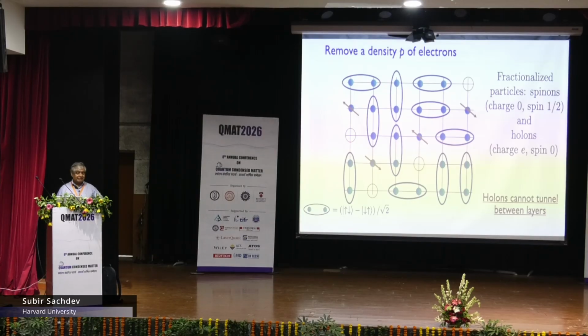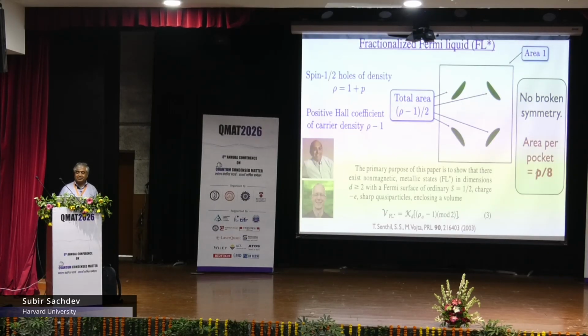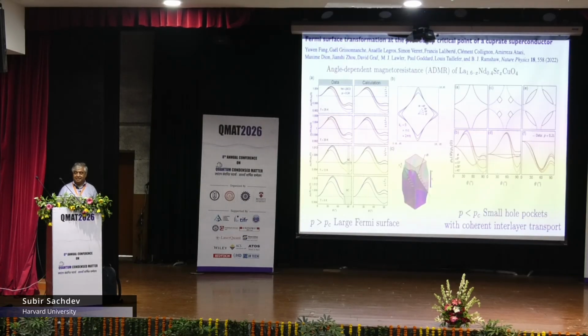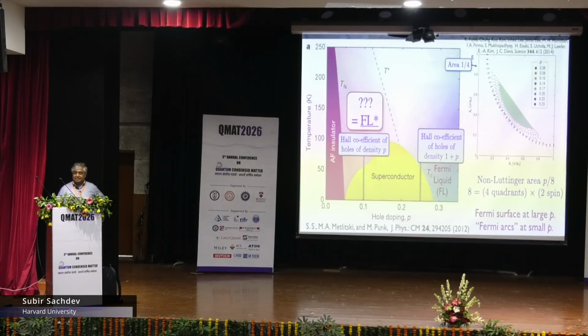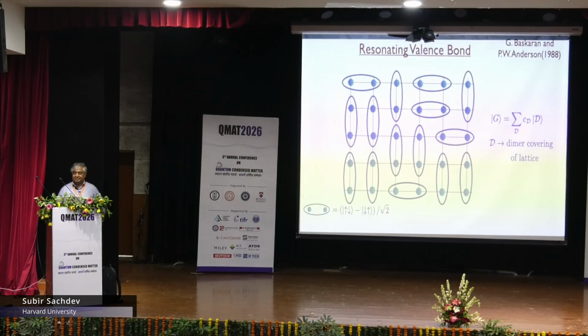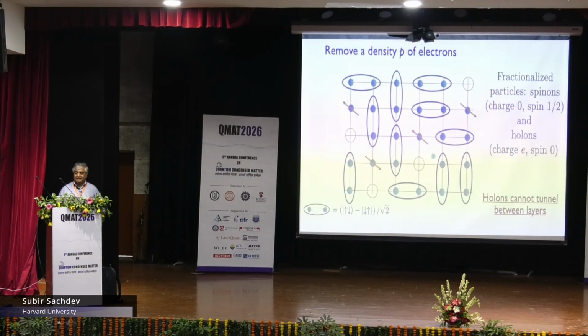Well, the recent experiment I showed you, in particular this one here, where you have coherent transport along this axis, even at low doping, tells you that this can't work because these holons cannot tunnel from one layer to the next. Only whole electrons can go from one layer to the next, because these are fractionalized particles that only make sense within this entangled state in a given layer.